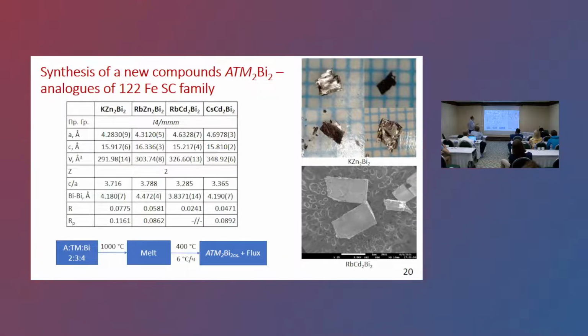We can see in the photo that these are very soft, foil-like crystals, and they are very easy to exfoliate, like a van der Waals compound. This was a very big problem for crystal structure determination, because it is not possible to take these crystals without destroying them. The layers change and move, and it is not a single crystal anymore if we take a small piece.